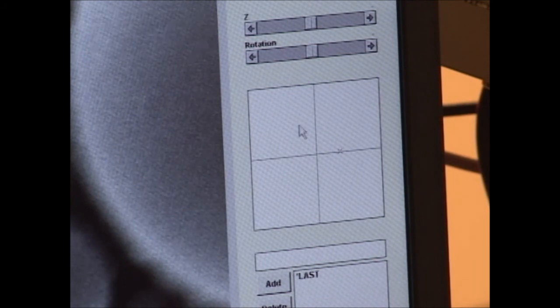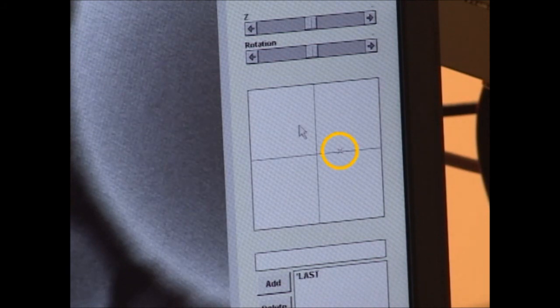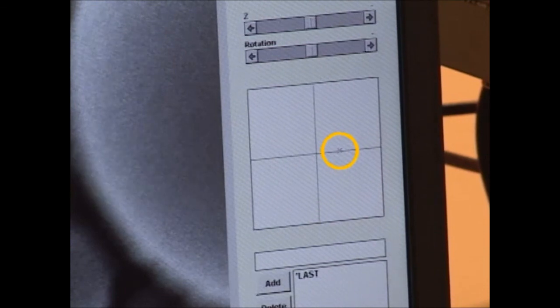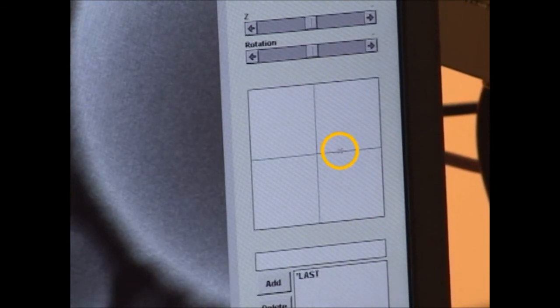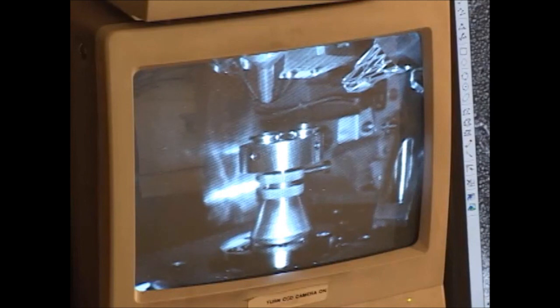And then I'm going to move it over to the next sample by just double clicking on this stage table along the positive x-axis where I know that next sample is located. So we're moving now to the tin. And now I don't know exactly what the clearance is. It's 10 millimeters from the gold on carbon sample to the detector. But the tin sample may be taller or shorter. So I'm going to recalibrate the stage height by repeating the procedure we did earlier.